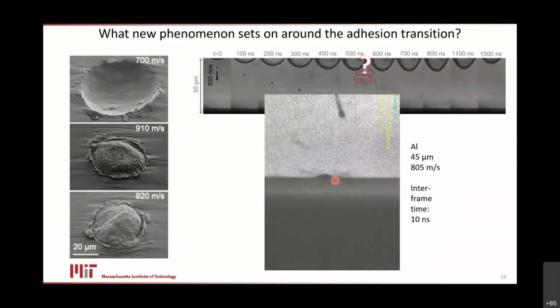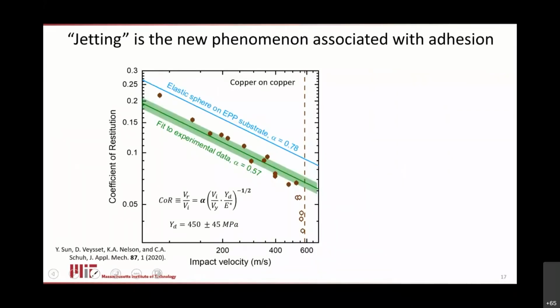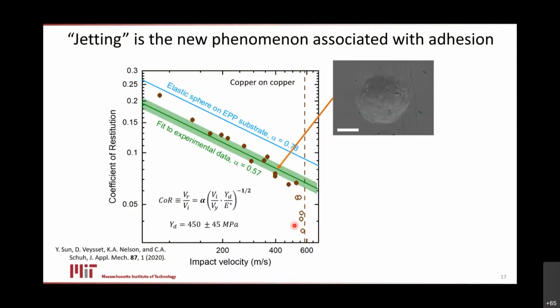Particles that stick have little solid state splashes that shoot out the side. So it's almost now like it looks like a meteorite impacting. We have jetting, we have ejecta shooting out the sides when these things stick. And that's our proposal. So we're proposing that, look, plasticity prevails for most velocities, but once we start to diverge, it's because this new phenomenon of jetting is starting to happen. And now that you have that hypothesis, you can go start looking for corroborating evidence.